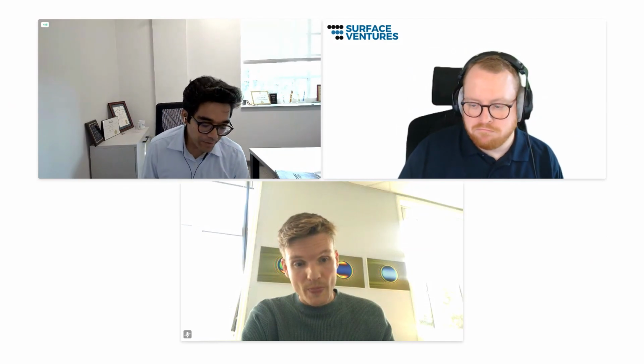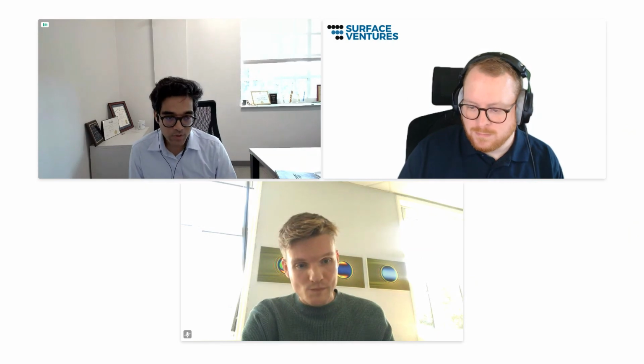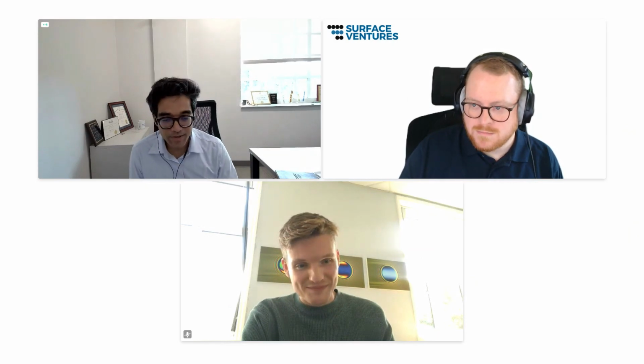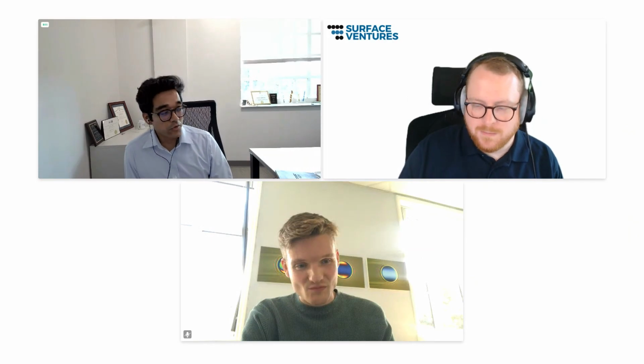Okay, so I'm assuming that this question pertains to the first part of my talk on catalytic alloys. We have not investigated it, and it will not matter under the test conditions that we are dealing with, because the tribofilm is formed by the reaction of ambient hydrocarbons, and the catalytic surface, the material, nickel, cobalt, chrome, is catalyzing that chemical reaction. So its melting point does not play a dominant role under these test conditions.